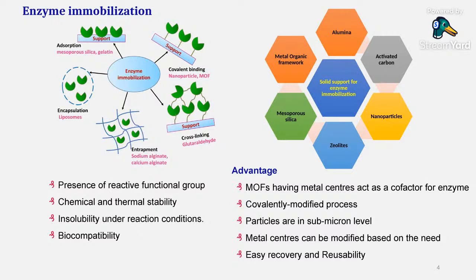The thing is, alumina or activated carbon or nanoparticles, people have used copper nanoparticles, iron nanoparticles, and they immobilized the enzymes over that and did the leather processing and other stuff. What happens during this methodology is, if you use iron nanoparticles for the immobilization of enzyme, iron imparts a brown color over the skin. It is undesirable because if I want white color leather or a different color, I can't use the brown color leather because I can't do the processing over that. I can't decolor that also.